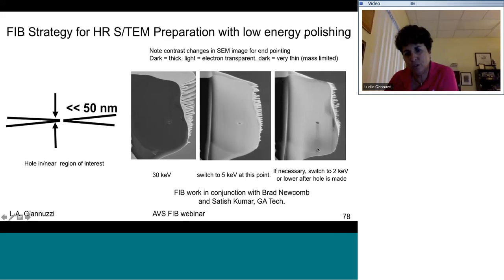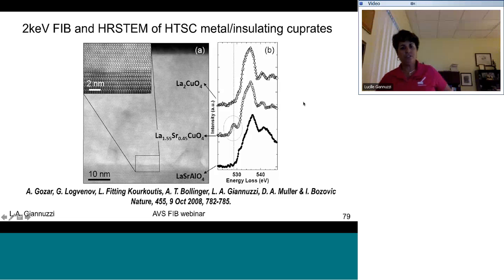And so this area is getting really thin. In fact, I've gotten to the point where I've actually punched a little hole through that. So this area right up against that hole is probably only about 20 or 30 nanometers. And now from this, I can stop here or I can switch to 2 kV or lower if I want to, just to hit each side for 30 seconds or so. Okay? So these are some examples working with collaborators that I did years ago.